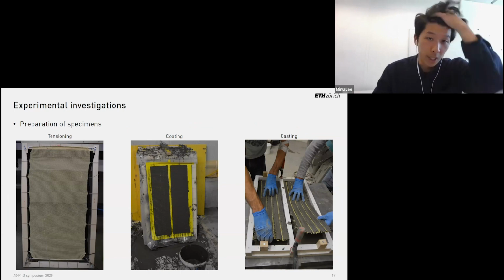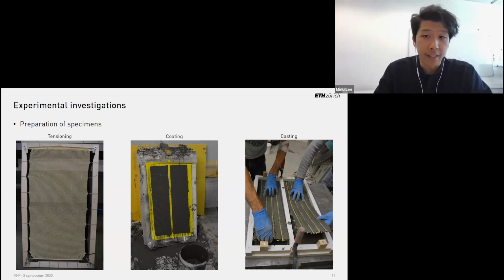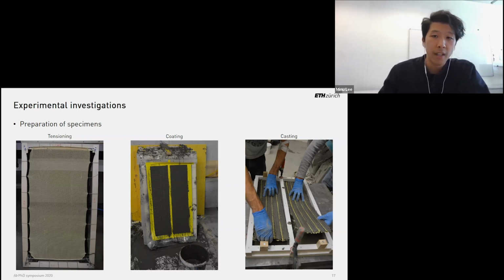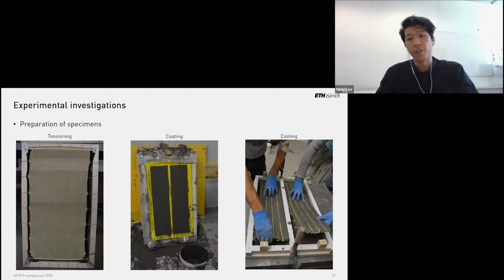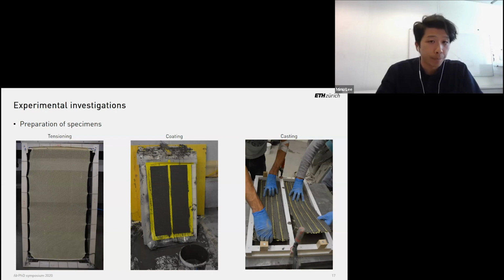So here's the sequence of production. Very shortly, textiles were tensioned in a wooden frame, then coated with either cement paste or epoxy, and after hardening, embedded in a fine-grained concrete matrix with 5 millimeter on bottom and 5 millimeter on top of the reinforcement. And the specimens were cast on a shaking table to minimize any air voids. For each individual configuration of knitting pattern, fiber material, coating, and bond ribs, we produced 2 specimens.